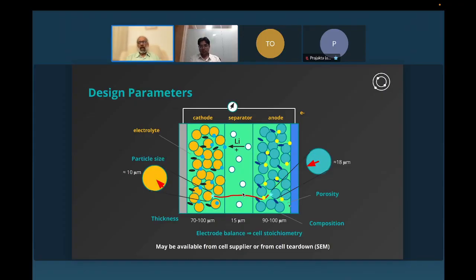What is the weight percent of the active material and the other components? So these are design parameters, and they should be available from the cell supplier, or if you have access physically to a cell, we can open up the cell and tear it down. There's a cell tear down, and through SEM imaging, an optical procedure, we can physically see the size of these materials. For example, the anode particle size can be very readily determined from the SEM analysis.